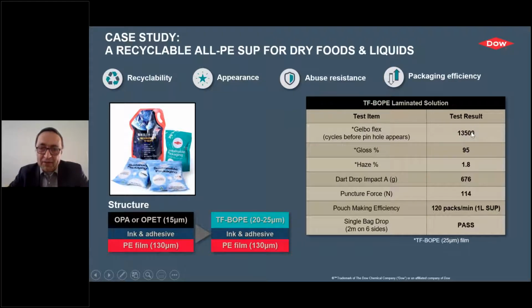We have a very flex crack resistant polymer. So after 13,000, we stopped the test because afterwards we still could have continued. It's much better than comparable material. Very good glossiness, very good impact resistance, very good drop resistance, which is important for these standard pouches.